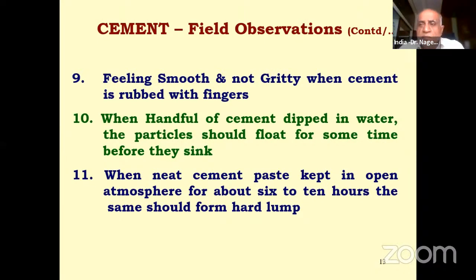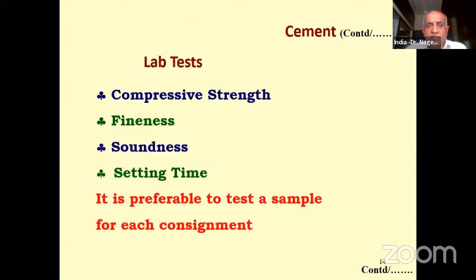So this is a very simple field test. You can keep a cement paste in the open atmosphere for about 6 to 10 hours. It should form a hard lump. This gives an idea of the setting or hardening property of the cement. Now, of course, these are only for places where you do not have a lab testing facility. In such cases, you can follow these physical observations. But when it comes to certifying the quality of the cement, we need to conduct many laboratory tests.